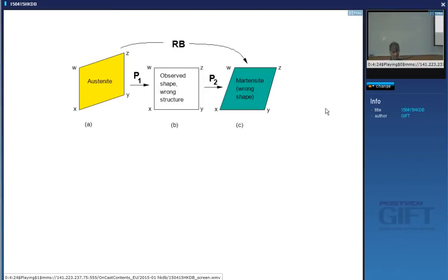Now, is there any kind of deformation which can make the shape equal to that, but which doesn't change the crystal structure? What kinds of deformation do not change the crystal structure, but change the shape? Yeah, twinning. What else? Slip. Yeah, so slip doesn't change the crystal structure, and similarly mechanical twinning doesn't do that. It simply reorients the lattice, right? So if I periodically slip this crystal so that the macroscopic shape becomes this, then the problem is solved. Yeah?